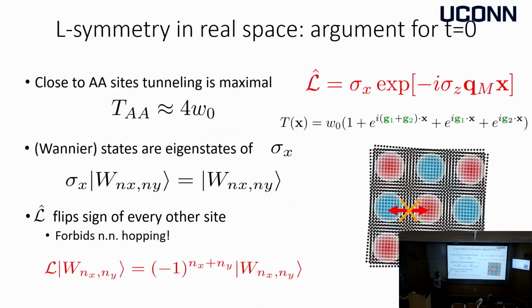So basically, my wave functions that are localized on this side, under the symmetry of the Hamiltonian, change sign. This becomes +1, this becomes -1. So nearest neighbor hopping is forbidden by this L symmetry. This L symmetry is not exact, but the corrections are of order twist angle to the 5th. So it's really a good symmetry at low twist angles.